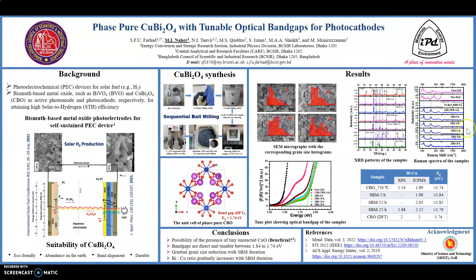For further confirmation of phase purity, we also did Raman spectroscopy, which is more sensitive than XRD. The results clearly show the phase pure CBO formation and gradual grain size reduction with sequential ball milling duration. The Tauc plot generated from the diffuse reflectance data displayed here shows that the band gaps are direct and tunable between 1.84 to 1.74 eV, which are summarized in the table.